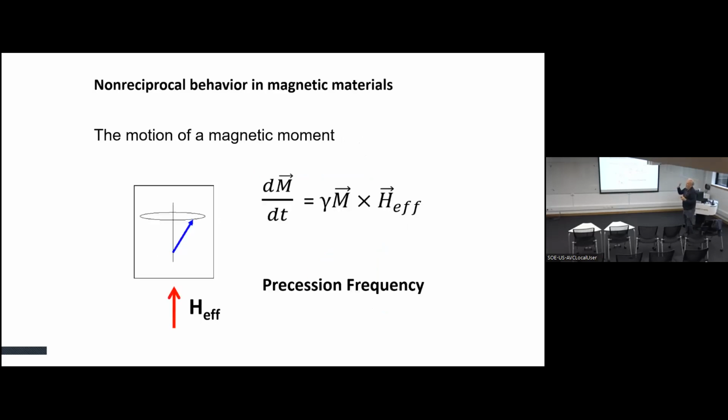Okay, in magnetic materials, all of these interesting effects come from the precession of the magnetic moments that they do in a microwave field, in an oscillating field. The magnetic moments go around like this, and it has a handedness. It only goes the way I drew it. It never reverses the other way. And that's what gives you fundamentally the sense of one direction.